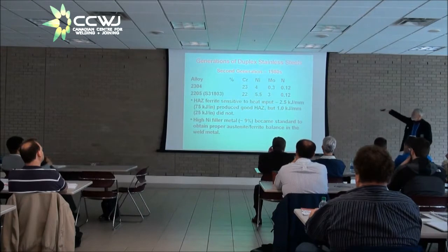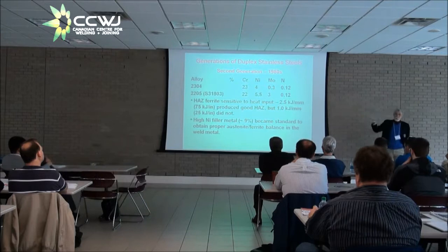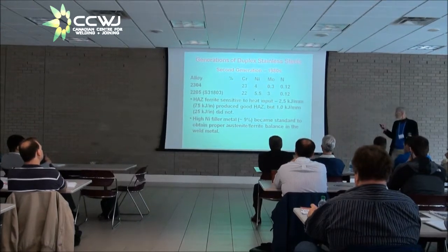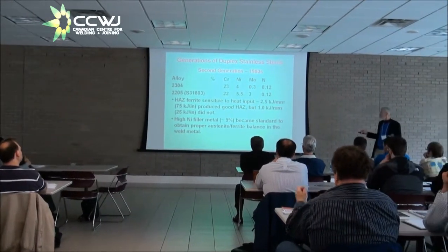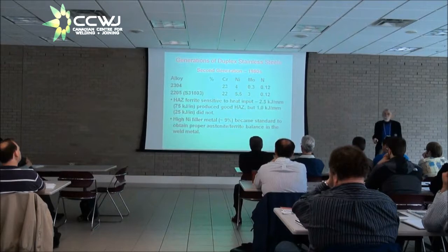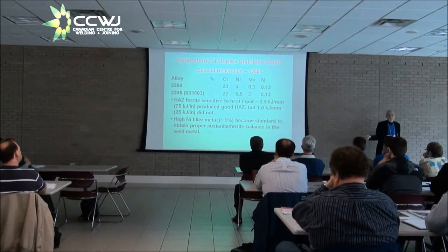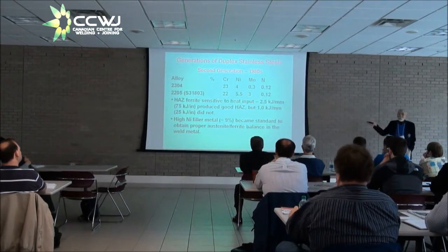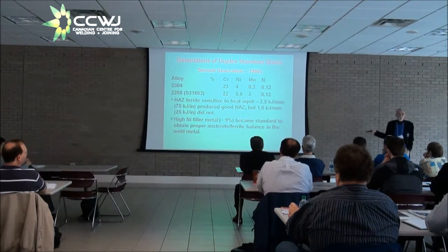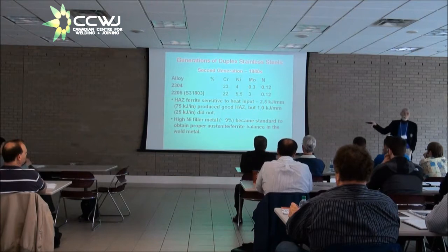And when this generation of base materials came about in the 1980s, it became very popular to adjust the filler metal composition to 9% nickel instead of 5%, so that you would get more austenite in the weld metal. That didn't do a thing for you for the heat affected zone. So you had to control the heat input in order to get a decent heat affected zone.